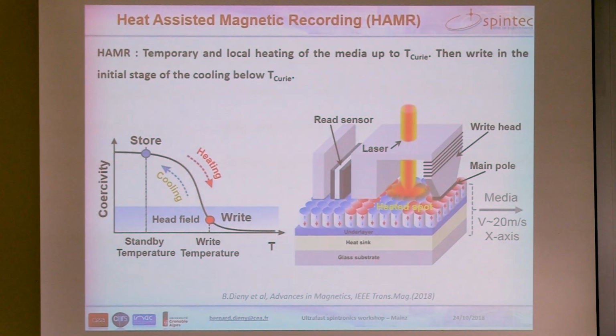So how does it work? This is a sketch of how it works. I explained that during write we need to heat the media to lower its anisotropy. This is done by focusing a laser on the media. And the media, as I said, is moving at 20 meters per second. But we need to write very small bits, and so we cannot just focus the laser on the media, because due to the diffraction limit, the heated spot would be comparable to half of the wavelength. In recording media, we want to write bits of the order of 20, 30 nanometers. So what we do is focus the laser on a plasmonic antenna, and this plasmonic antenna emits a near-field electromagnetic wave, which is used to heat the media locally.